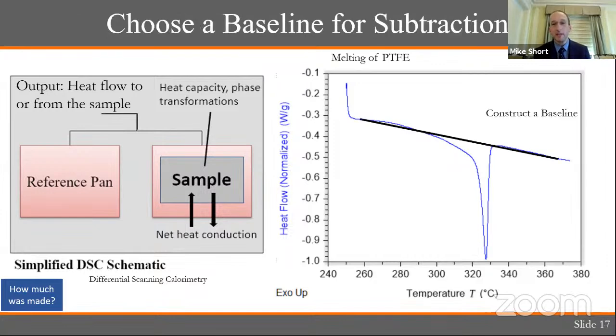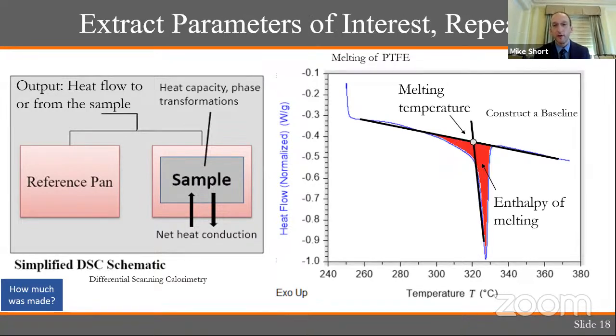You keep on heating, draw a background baseline, and the shape of the curve you draw is not so important, we found, as long as you're consistent. And then you can do some studies on this, where you can look at the area of this peak to look at the total amount of energy required to melt the Teflon. You can extrapolate back to the onset temperature of melting, or all sorts of different things in order to figure out what's going on.